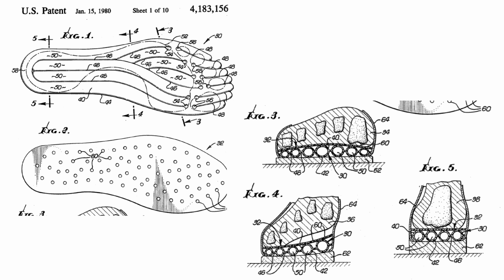The physical properties of the selected insole materials, including tensile strength, modulus of elasticity, fatigue resistance, and heat sealability, are very important in a product such as the insole, which is subjected to an extremely demanding duty cycle when worn in a shoe for the life of the shoe. The average person walks approximately 2 to 3 miles per day, which approaches 1,000 miles per year. Assuming 1,000 paces to the mile, the insole encounters 1,000,000 cycles per year. Each of these cycles compresses the insole to about 25% of its freestanding inflated height.